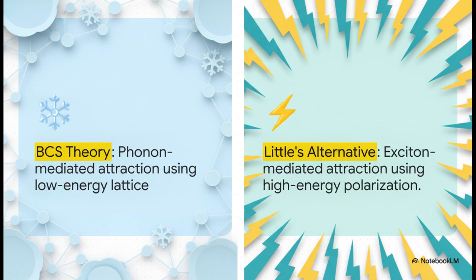Well, this brilliantly illustrates the contrast between the traditional view and Little's vision. In standard metals, which are described by the famous BCS theory, the glue that holds the pair together is a phonon. That's a slow, low-energy vibration of the crystal lattice. Little, however, proposed an excitonic alternative. He suggested using the incredibly fast, high-energy electronic excitations within those organic dye side chains to bind the electrons together. Because electrons are practically weightless compared to atomic nuclei, the energy scale of these excitons is vastly higher than phonons. And, in the math of superconductivity, a higher energy glue theoretically means you get a much higher transition temperature.